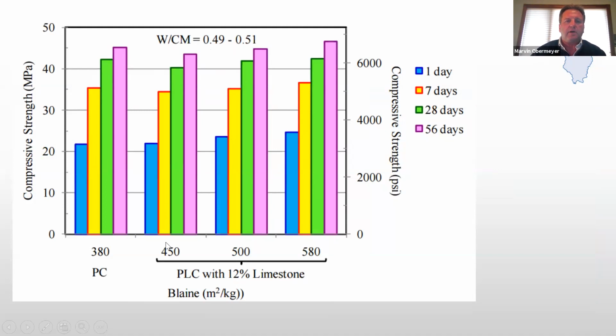And then we made Portland limestone cement. I shouldn't say we, this is data from, I think, PCA. They made Portland limestone cement at 3 different Blaines. They made it finer, to 450, 500, and 580, and at 580 you're approaching Type 3 cement fineness. My rule of thumb is about 600, give or take. At 450, you can see the 28 days were a little bit lower. At 500, it was higher, and this is even higher yet.